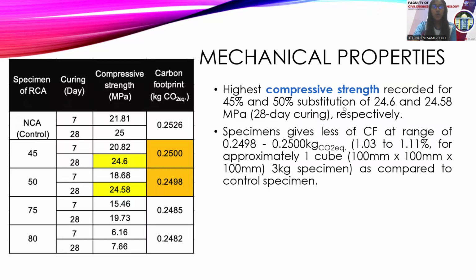Highest compressive strength was recorded for 45% and 50% substitution, at 24.6 and 24.58 MPa for the 28 days curing, and this is the highest value for the two replacements. And then the specimen gives a lower carbon footprint, in the range of 0.2498 to 0.2500 kg CO2 equivalent, an accumulated 1.03 to 1.11% reduction. So it is approximately for 1 cube, and the sizing for the 3 kg specimen as compared to the control specimen. This will be more cost effective.